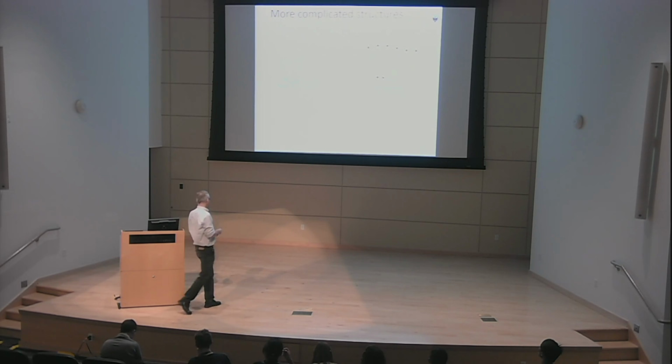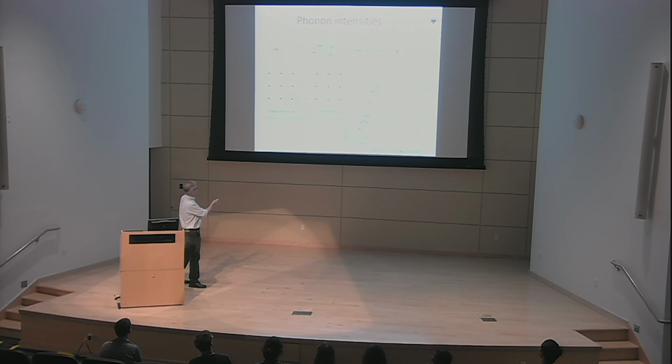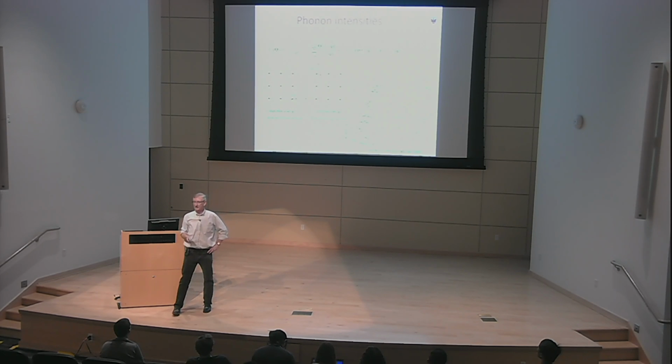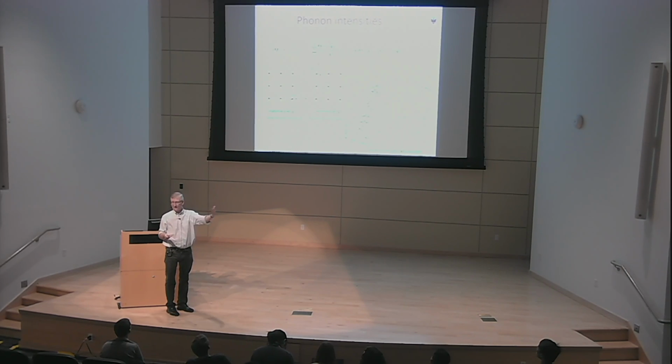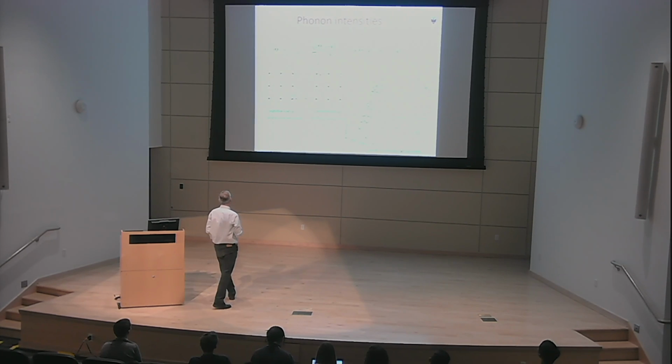And actually, the cross-section for 1 phonon processes, you can see here, this is related to the double differential cross-section. It goes like q squared. It goes like the momentum transfer squared. So that's characteristic of single phonon scattering. If you had multiple phonon scattering, what you might naively generalize, and it would be correct, is that the cross-section for multi-phonon scattering would go like q to the 4th or stronger, actually. Okay. But like I say, you've got to figure out a way that you can conserve energy and momentum.